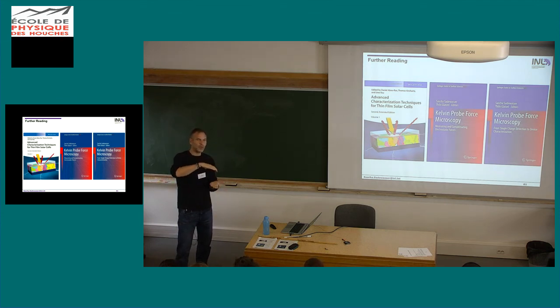So it's much easier to illuminate from the back if you have a transparent solar cell, like a superstrate solar cell, and you can measure on cadmium telluride. And what they did, I think they illuminated with one sun, and they adjusted the voltage. They used a controller on the voltage to get to zero current. So they were measuring in contact, measuring currents, and then used a controller to apply the voltage that would nullify the current. And then they said they measure directly the open circuit voltage from grain to grain. So this is much more convincing to me than the other method.